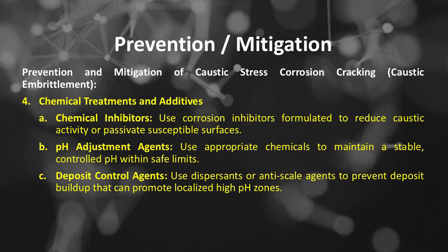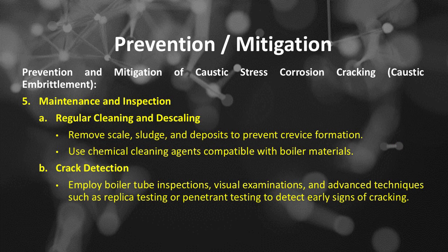Number 4 of prevention and mitigation of caustic stress corrosion cracking or caustic embrittlement is chemical treatments and additives, which includes, number A, chemical inhibitors. Use corrosion inhibitors formulated to reduce caustic activity or passivate susceptible surfaces. Number B, pH adjustment agents. Use appropriate chemicals to maintain a stable, controlled pH within safe limits. Number C, deposit control agents. Use dispersants or anti-scale agents to prevent deposit buildup that can promote localized high pH zones.